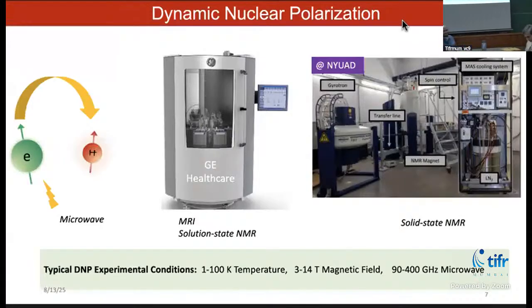One thing is to quickly melt the sample. The metabolite is at 1 Kelvin. It is quickly melted and injected in a certain magnetic field such that there are no level anti-crossings. You don't want the polarization to be dispersed. You want polarization to remain on the spins which were hyperpolarized. So there are definitely techniques involved in doing it in a way that we don't lose polarization quickly. But for the case of solids, for magic angle spinning NMR, one does hyperpolarization and NMR measurement in the same instrument. So we don't have to shuttle the sample. And it has its own advantage because one can do phase cycling, one can do 2D NMR, the way we do conventional NMR, in the solid state.